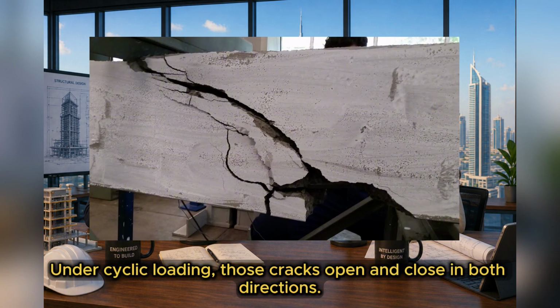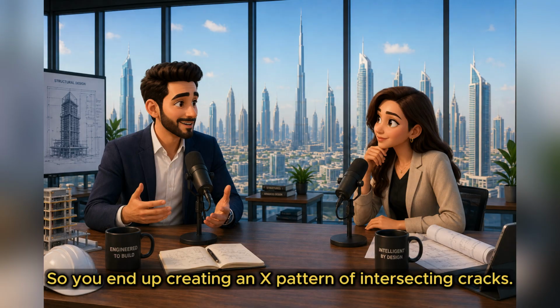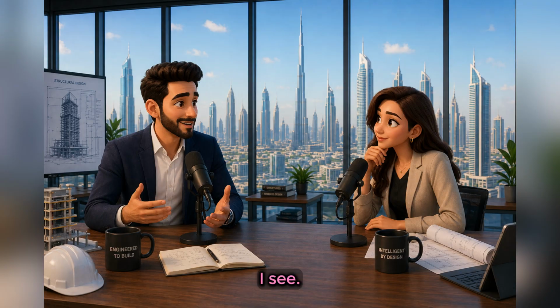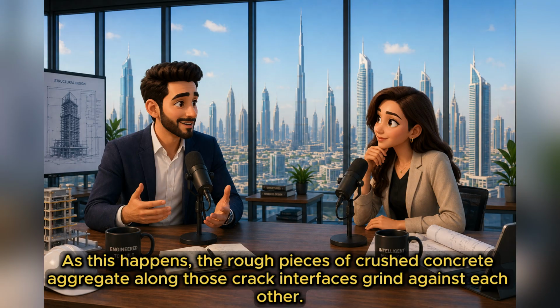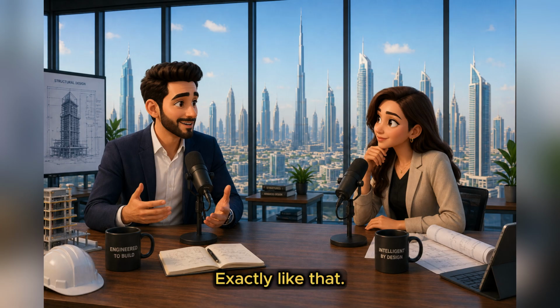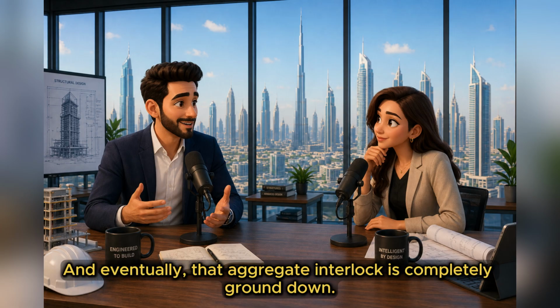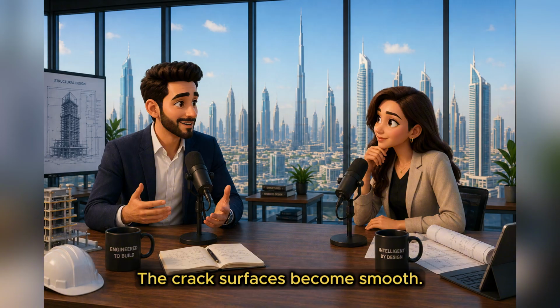Under cyclic loading, those cracks open and close in both directions. So you end up creating an X pattern of intersecting cracks. Oh, I see. As this happens, the rough pieces of crushed concrete aggregate along those crack interfaces grind against each other. Like sandpaper. Exactly like that. And eventually, that aggregate interlock is completely ground down. The crack surfaces become smooth.